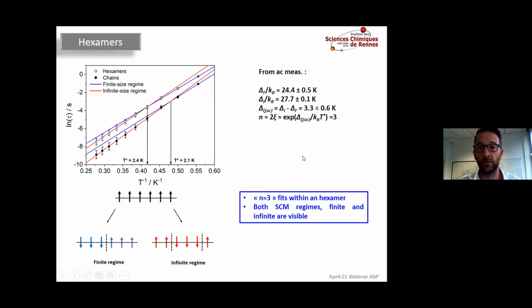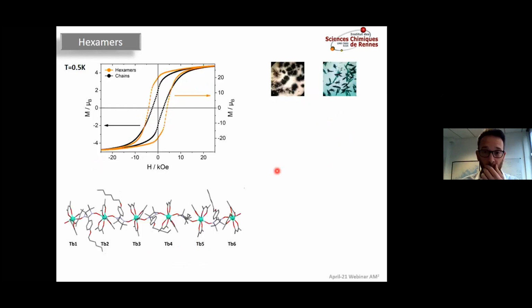So we can calculate the correlated unit. We can see that we have 3 units, so it fits quite well in the hexamer. And we can observe both the finite and infinite regime on a single chain magnet, but on a finite molecule. So just measure the hysteresis. We have actually a better hysteresis than what we observe on chains, probably, but we are not sure, because we are seeing things that are much more linear than the chains that are curled. So maybe the couplings are better.